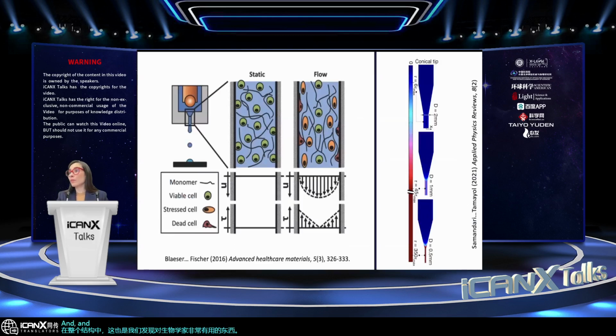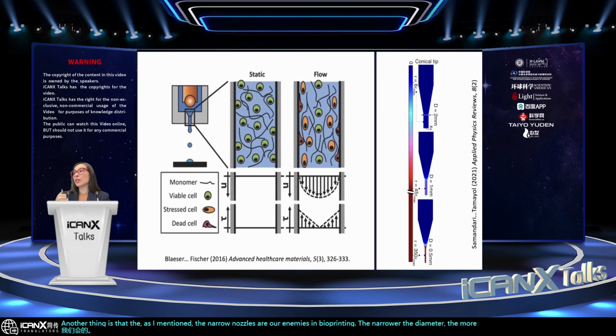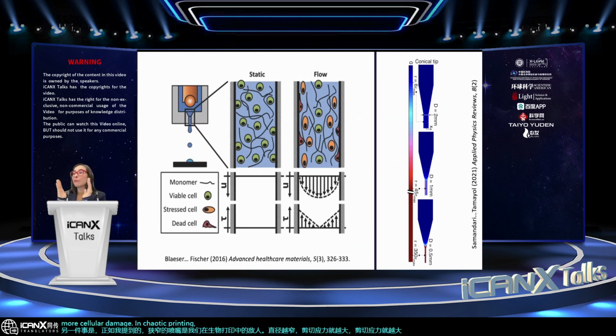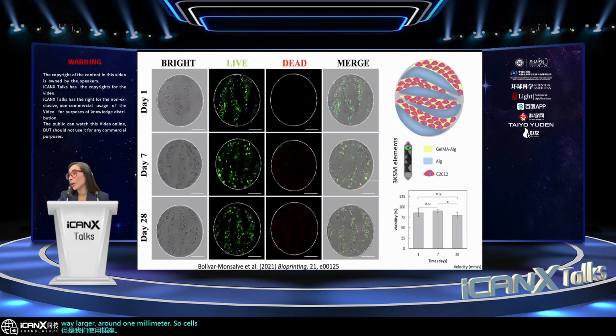And well, another thing is that, as I mentioned, the narrow nozzles are our enemies in bioprinting. The narrower the diameter, the more shear stress, and the more shear stress, the more cellular damage. In chaotic printing, we can get very small features. The resolution, meaning the size of the layers, can be very small, but we use outlets way larger, around 1 millimeter. So cells feel happier that way when they are extruded through large nozzles.